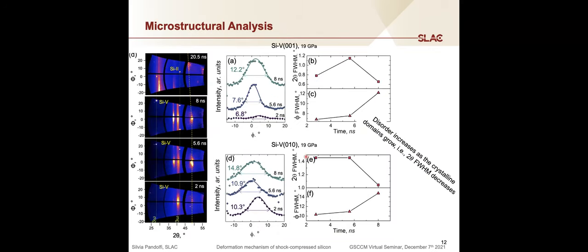So as I was saying, there is this microstructure evolution that we have tried to quantify. For doing that, we have taken lineouts of these X-ray diffraction peaks along the phi angle, and we've analyzed their time evolution. And we see that the full width at half maximum of the peaks along phi, which can be indicative of mosaicity, so of the different orientation of crystallites present in the sample, or can be indicative of the development of rotation and so defects in the sample, increases consistently with time.